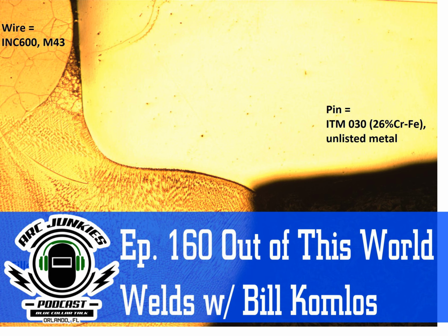They get worried about triaxiality, where you're locked up in all 3 planes, longitudinal, transverse. Yeah, well, that's longitudinal, parallel, axial. I'm lost now. I'm thinking about too many things, but it's 3 dimensions, okay? Up, down, sideways, and in and out. But if you can get one of those planes to be in compression, the rest of the structure is going to jiggle nicely. And we're just doing that by shrinking the steel, and I can do it in real time. We shrink it while the welder's welding on it.